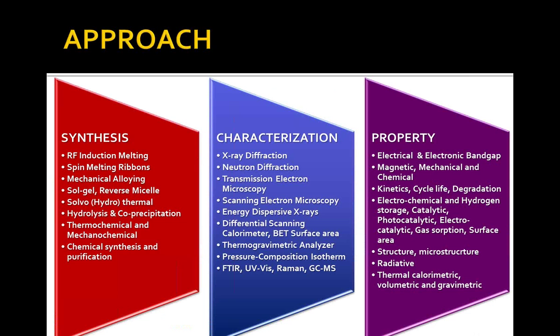A number of methods we often use for making the materials. For synthesis, we use radio frequency induction melting, spin melting, mechanical alloying, sol-gel, reverse micelle, solvothermal, hydrolysis, thermochemical, mechanochemical, and chemical synthesis and purification. These are various synthesis methods where you can produce hydrides, and we use characterization like X-ray diffraction, neutron diffraction, transmission electron microscopy, scanning electron microscopy, energy dispersive X-rays, differential scanning calorimetry, BET surface area, thermogravimetric analyzer, pressure composition isotherm, Fourier transform infrared spectroscopy, UV-Vis, Raman and GCMS.